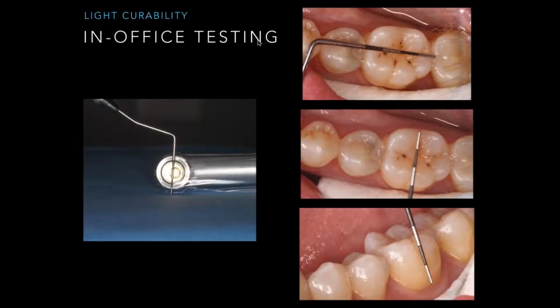Composites take a lot to place, and you want to make sure that when you're doing it, they're going to leave with an adequately, properly cured restoration. In this example that I'm showing you here, I'm using a smart light, and I'm showing you the width of this, and you want to make sure that your beam is able to measure. And again, with this light, when you're considering curing a molar, you're going to have to move. If you think you can get the entire molar width of that, let's say perhaps an MOD restoration, you're not going to be able to do that. You're going to be able to cure one aspect of that proximal box mesially and then move to the distal or vice versa. So it's really something you need to be concerned about, because the combination of that beam is the actual width. You need to make sure you measure and you know that you have your proper light curing, proper distance, proper width, proper placement.